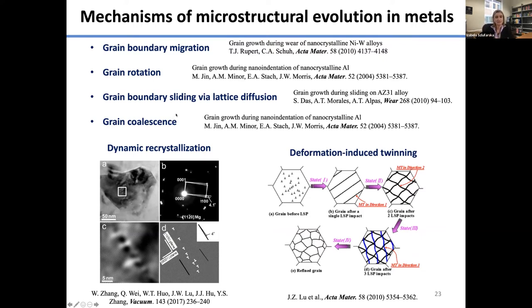Some of the mechanisms that have been shown to lead to grain refinement are dynamic recrystallization, as well as another example, deformation-induced twinning. This is one type of dynamic recrystallization shown here, where dislocations are introduced into the grains. They can arrange themselves into cells and sub-boundaries and eventually develop new grain boundaries and refine the grain size, which improves their wear resistance.